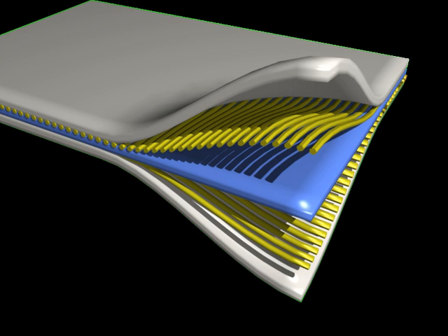The strength of a composite is bounded by two loading conditions as shown in the plot to the right. If both the fibers and matrix are aligned parallel to the loading direction, the deformation of both phases will be the same, assuming there is no delamination at the fiber-matrix interface. This isostrain condition provides the upper bound for composite strength, and is determined by the rule of mixtures.